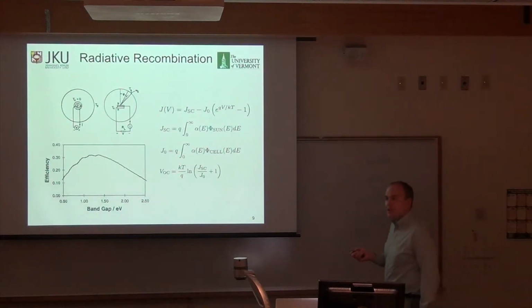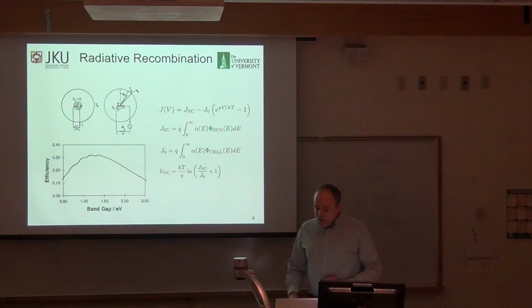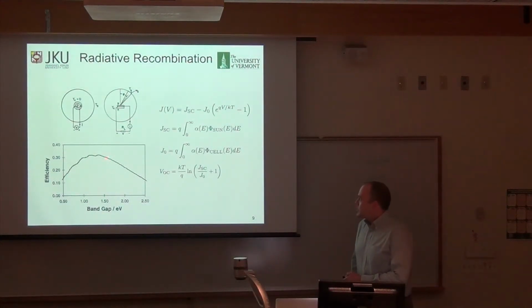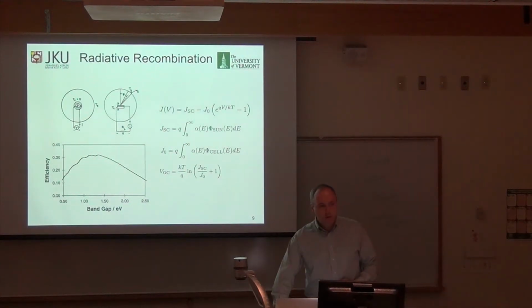And that shifts your theoretical maximum from the Shockley-Queisser limit to this curve, which has a maximum at about 33%, at a band gap of closer to 1.3, 1.4 electron volts. This was the result of Shockley and Queisser, and trying to get solar cells to this limit has been the goal of solar cell research ever since.